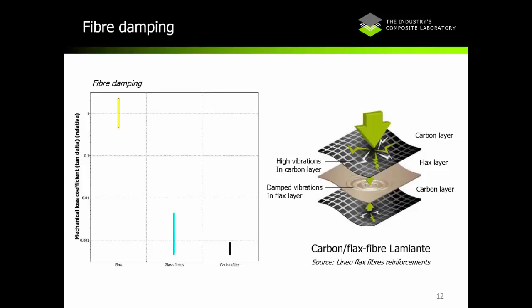Another great property with natural fibers is damping. So again, I've generated this in Granta. We have the mechanical loss coefficient on the y-axis, and you can see that the fiber damping is about 3 orders of magnitude higher than the glass fiber and the carbon fiber. This is why carbon fiber and glass fiber make such good springs, because they don't lose a lot of energy when they're bending.